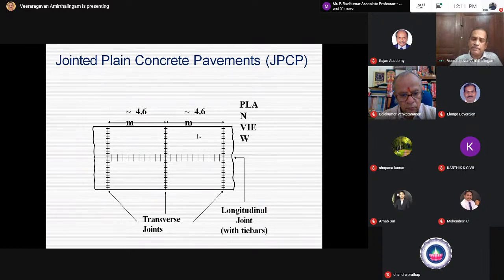Can I reduce? Yes, possible. How do you reduce? The edge load stresses cause more or more severe distresses. I can go in for a wider shoulder, a concrete shoulder. If I extend the width of the pavement from 3.5 to maybe half a meter either side, or 1 meter either side, then the edge load stresses are reduced, with the result that thickness can be reduced.